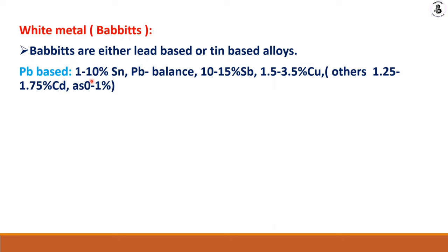1 to 10% tin, lead in balance, 10 to 15% Sb, 1.5 to 3.5% copper, and remaining others as 1.25 to 1.75% cadmium and 0-1% arsenic.